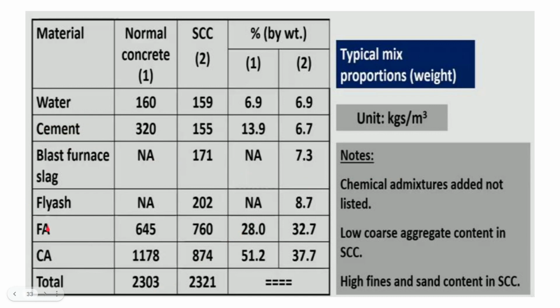Again, if we look at the fine aggregate content, the sand content, in normal concrete it is around 28%, whereas in SCC it is around 33%, almost 5% more. So the total powder content is 9% more and fines 5% more. So 9 plus 5, almost 14% extra finer material compared to normal concrete, and that's why the coarse aggregate value is also less by around 14%.